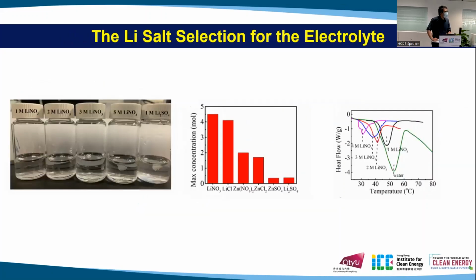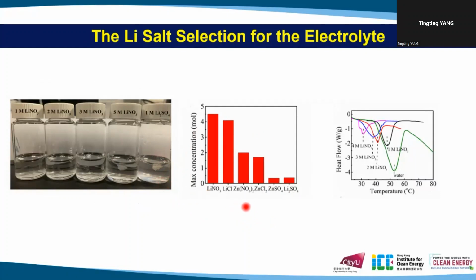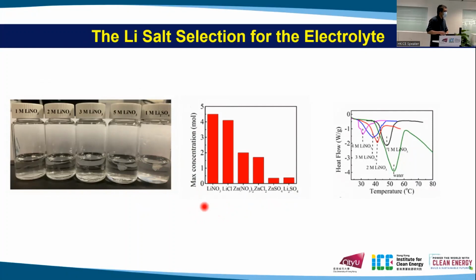The most important thing for this hydrogel application is that we should choose an appropriate lithium salt, because you can see from this figure, even with very low concentration lithium sulfate, the water will be drained out by the electrolyte, and it will stop working. If we use this electrolyte, the inner resistance will be huge, even at room temperature. After we tried several lithium salts, we found that the hydrogel has the highest tolerance for lithium nitrate. We also tested the LCST at different concentrations. Then we finally used 1 molar lithium nitrate as the electrolyte.